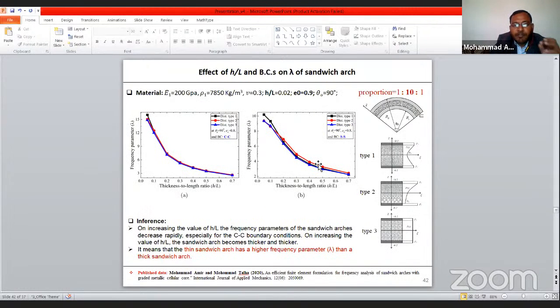Here, the effect of thickness to length ratio h by l and boundary conditions on the frequency response of the sandwich arch. Here, I have considered opening angle theta is equal to 90 degree, and other parameters are given. By increasing the thickness to length ratio, the frequency parameter is decreasing irrespective of the boundary condition type.